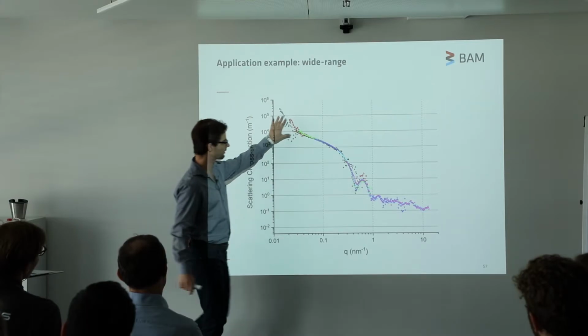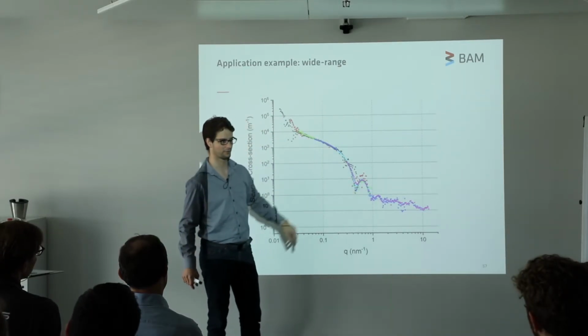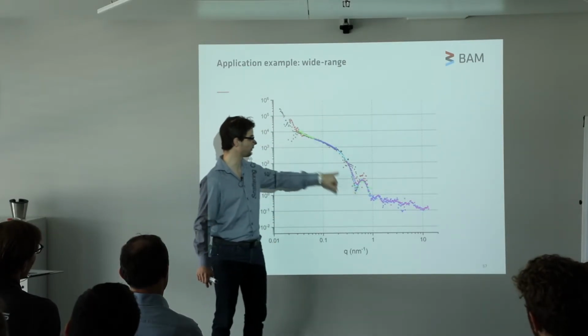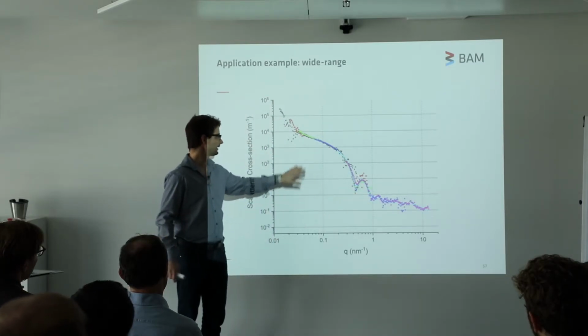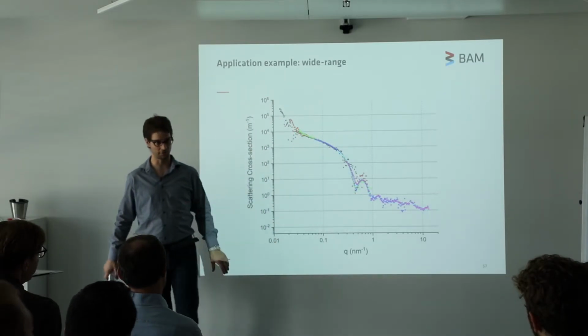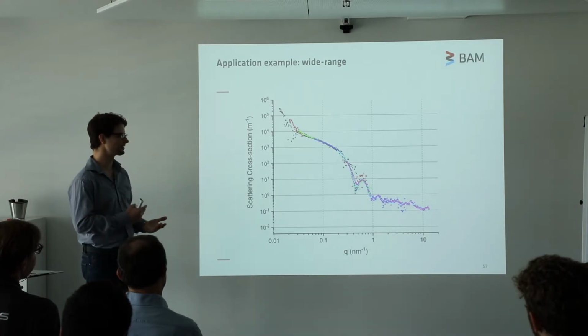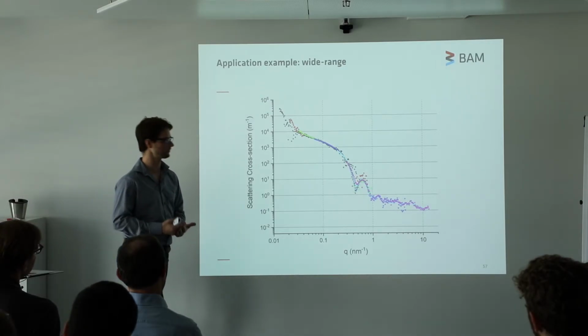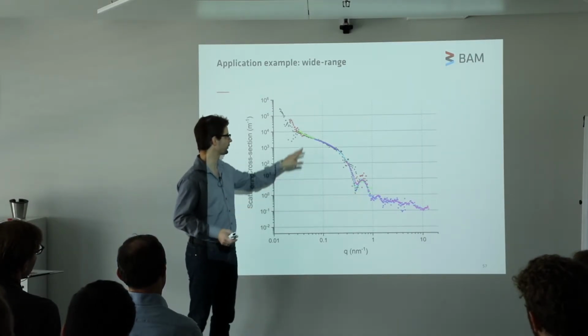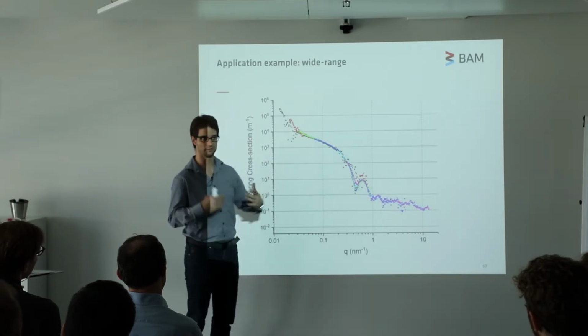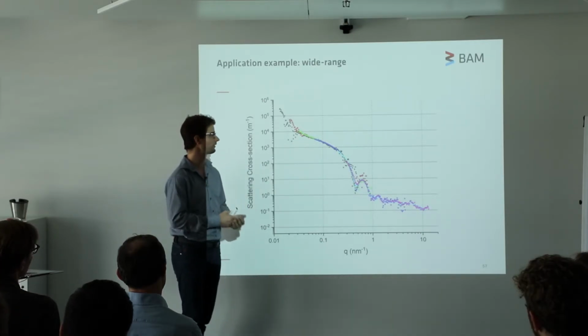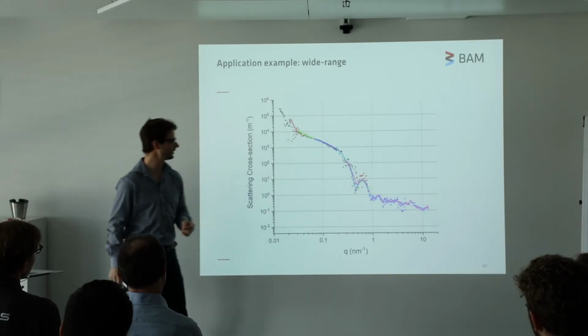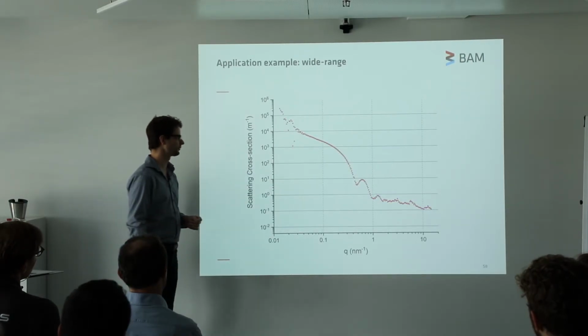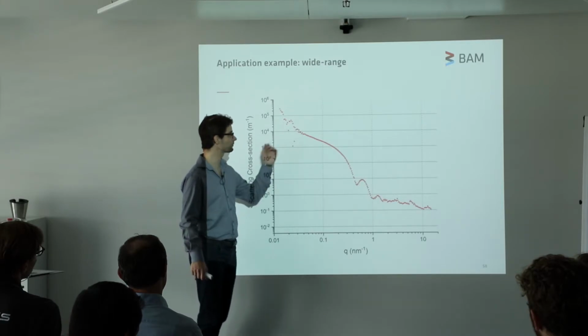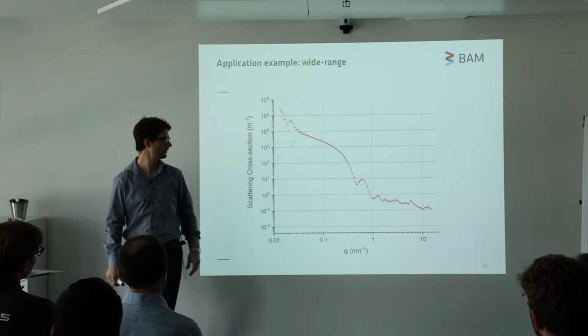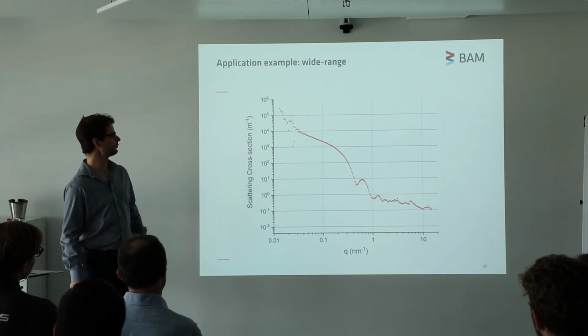All of our data sets are in absolute units, so this is the way it comes out of the machine. They all overlap automatically. And now we have a data merging script which merges these data sets taking the uncertainties into account. So if you have data points with a very small uncertainty, so very good data points, they're weighted much more heavily than data points with a large uncertainty. And in the end, you get a scattering pattern like this. This, by the way, is the tobacco mosaic virus, which we measured, I think, 2 weeks ago.